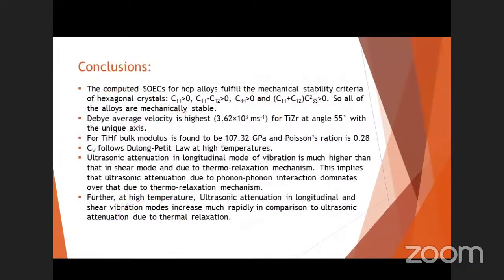These are the conclusions of the results. Due to the SOECs and these conditions, we can say that the alloys are mechanically stable at higher pressure and temperature. We can also say that the Debye average velocity is the highest for TiZr at 3.62 kilometers per second.